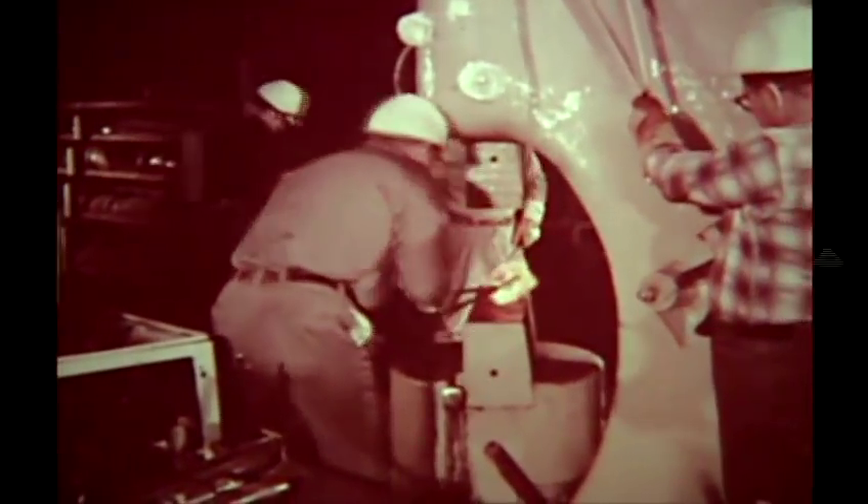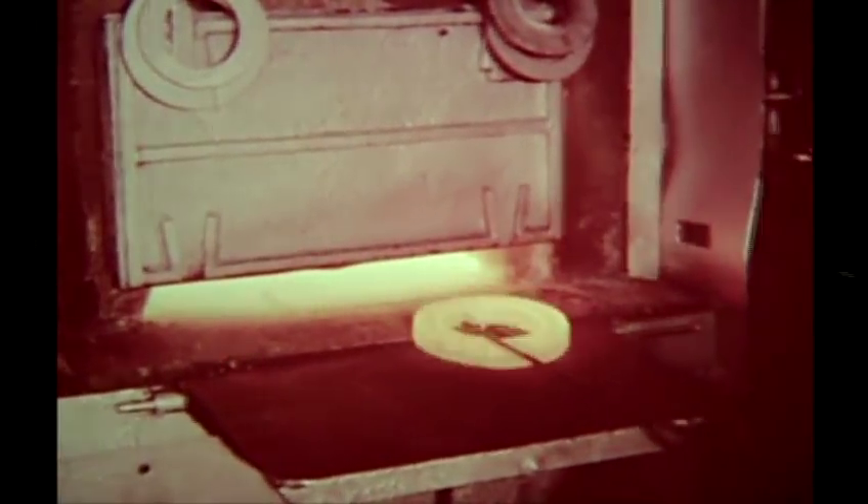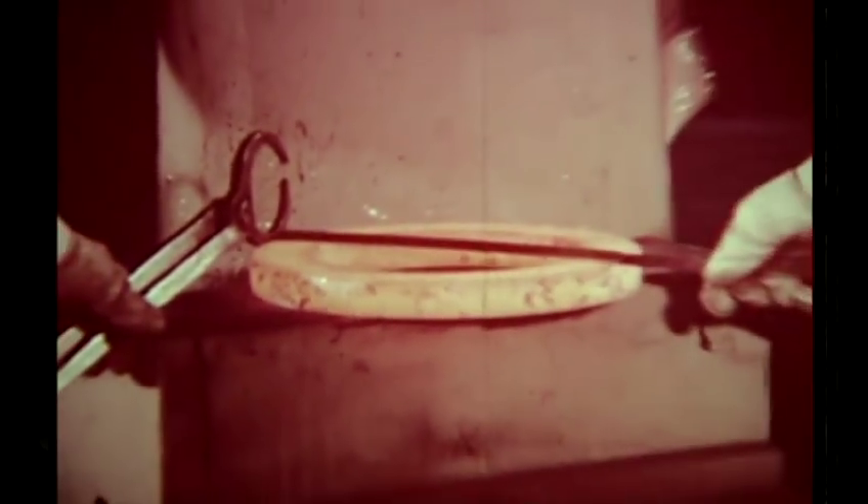Typical parts produced from an inventory like this are high-quality forged rings. A solid steel block of exact weight is cut and heated to forging temperature. When the metal block has been flattened and rounded, a slug is punched from the center. At this stage of shaping, the ring is colorfully known as a donut. Manufacturers forge rings measuring in diameter from inches to many feet. The forging process produces a solid ring with unbroken flow lines — this smooth grain flow adds strength and toughness superior to that of cast or welded rings. As in most forging operations, this process of preforming the hot metal to desired shape is accomplished in a series of heating and forging operations. Rings are used extensively in anti-friction bearings, rocket and jet engines, gears, turbines, missiles, and many other applications requiring high-quality circular shapes.